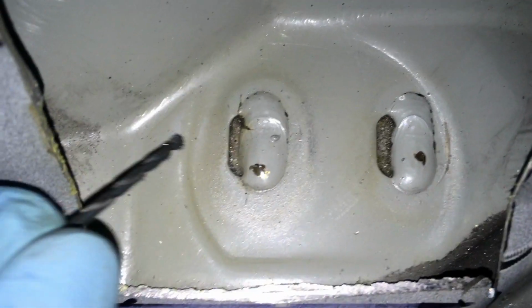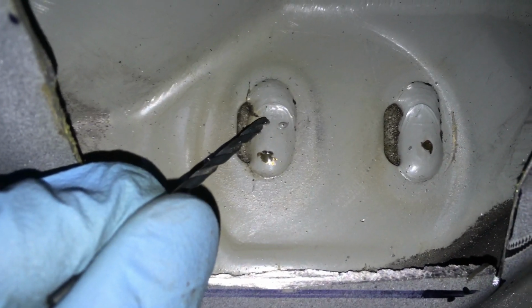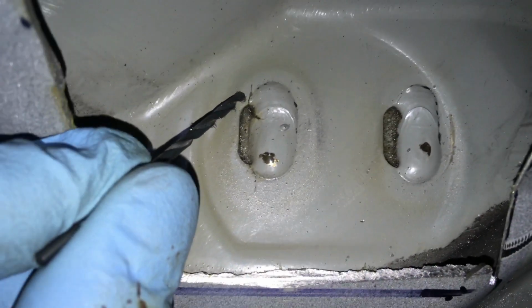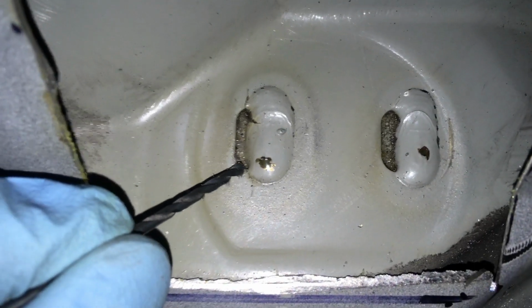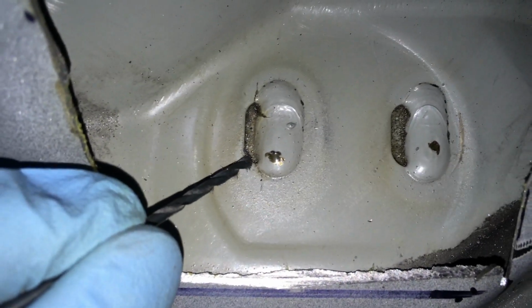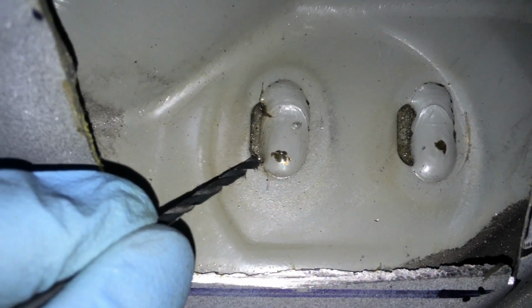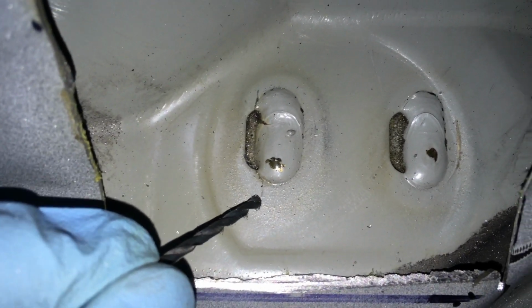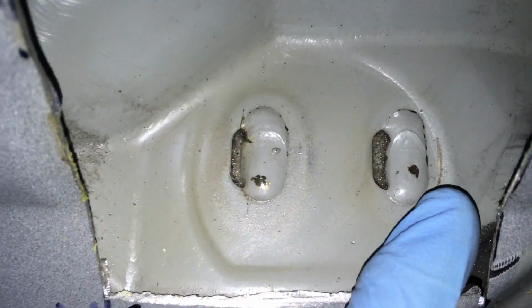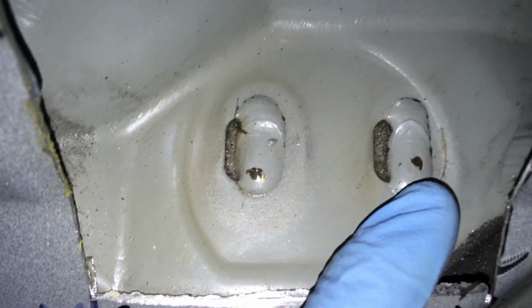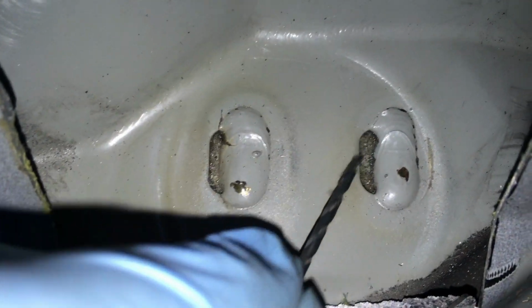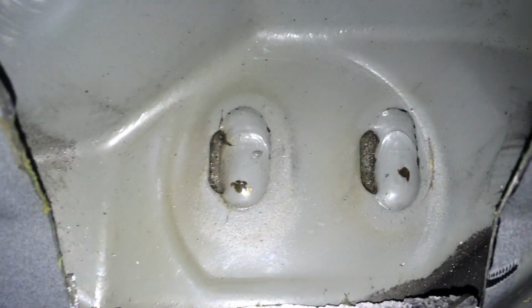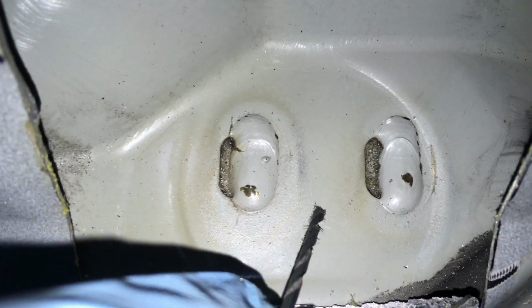So this is a MIG weld and this is a MIG weld. This one looks okay, doesn't look to be any cracks coming out of that one. This one's got a crack somewhere around about there in the middle of the weld, curving round that way and going up to about here at the moment. Then there's another crack forming somewhere around the corner of this MIG weld where it attaches to the panel and is just going outboard to around about there. So we need to centre punch, stop drill them, and then we'll also remove these MIG welds because these are poor penetrating MIG welds. They certainly don't fill up all the laser cut gap that the panel came with from factory. And they're always cracking, so we're going to remove those and then apply our own MIG welds to attach the threaded receiver under here to this rear axle carrier panel cavity cover, as we call it.